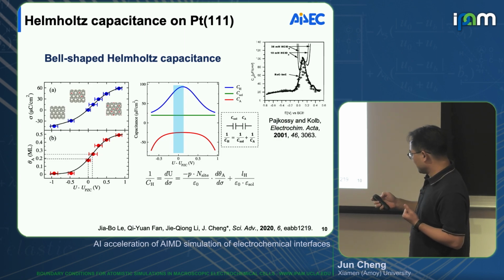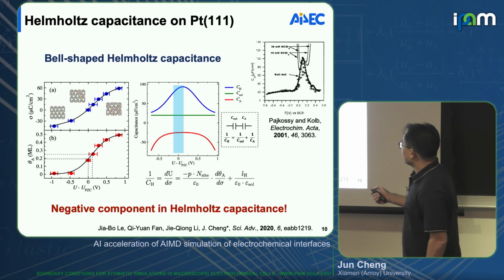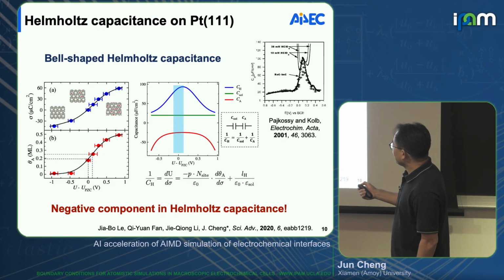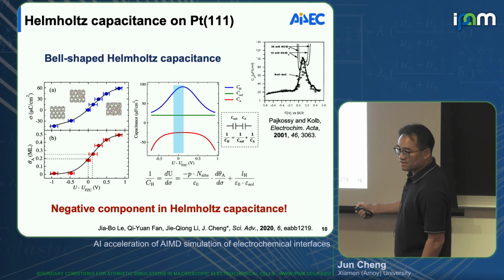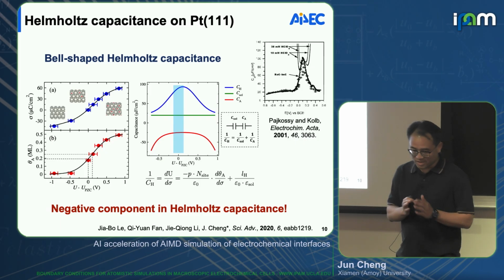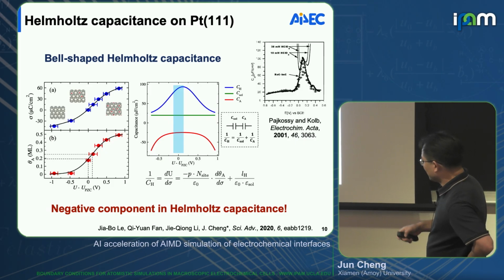So maybe just one more word, why this peak is slightly more positive than the potential of zero charge is just because the maximum of this curve comes with the middle of this adsorption isotherm, right, from zero to half monolayer. So the middle point is actually around 0.25 or so, but at potential of zero charge, this adsorption is around 0.2. So that gives this slightly more positive than the potential of zero charge.